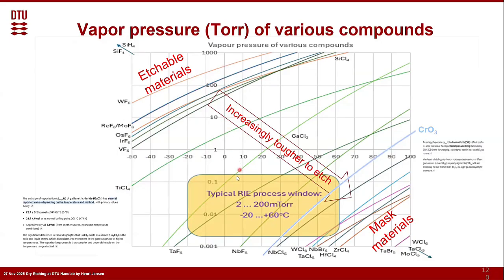And here you see even a clump of materials passing a typical reactor condition, which is between, let's say, -20 and +60 degrees Celsius. It can be higher, of course, but these are the typical ones. And normally the pressures in the reactor in the reactive ion etch mode is between, let's say, 20 and 200 millitorr. Of course, here also there can be changes, but this is a typical window. Now, everything which is below this window, where this line is passing by but doesn't touch it, means that the vapor pressure is so low, it will never happen.